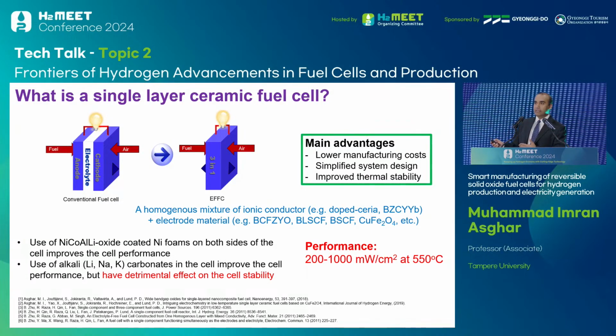The main advantage of this cell structure is that we have simplified system design and lower manufacturing cost, and at the same time improved thermal stability. Because in three-layer cells, when you have materials with different thermal expansion coefficients at high temperature operation, you cause lots of thermal stresses in the cell. However, with the single-layer cells, we avoid all those problems.